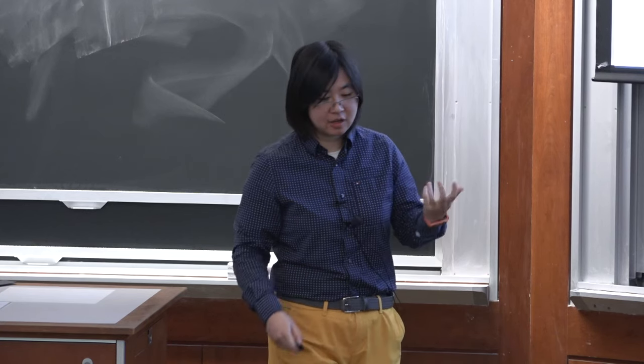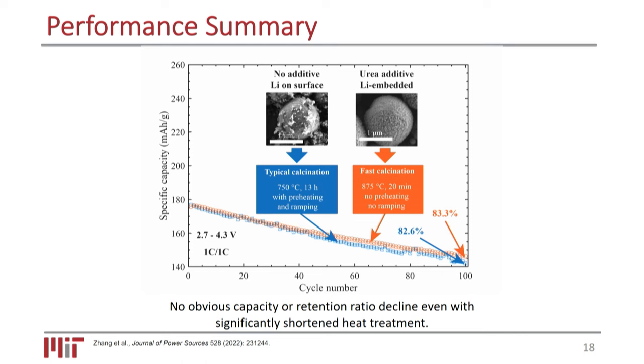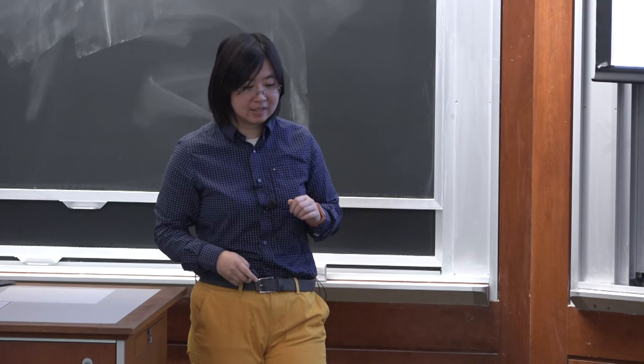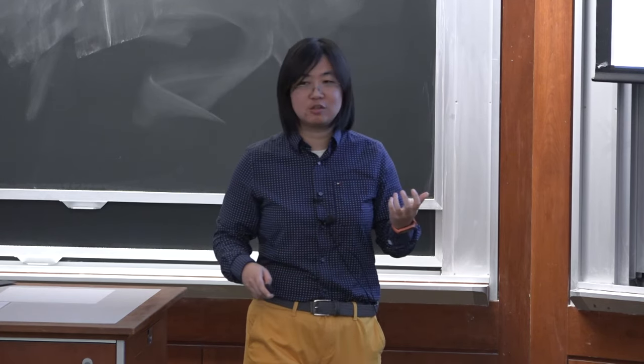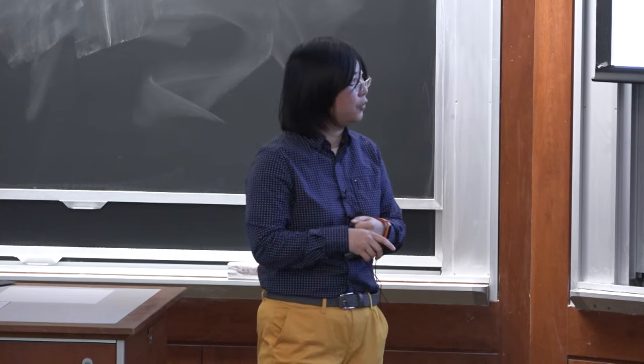And here is a comparison between the two. What this figure is showing you, without diving into the details, is that we can achieve essentially the same performance in terms of the capacity of the battery as well as the retention after cycling. So both the stability and the capacity of the material can maintain the same level by adding a little bit of urea in the precursors, and we can significantly reduce the calcination time and energy consumption. And compared with the literature using other materials, we still see very, very compelling performance.